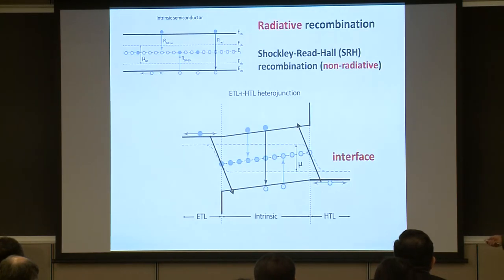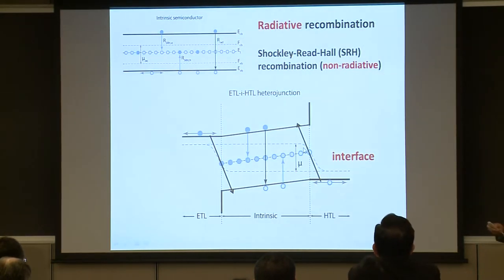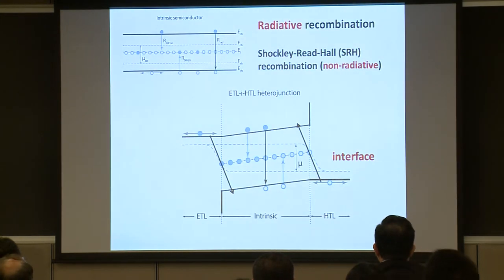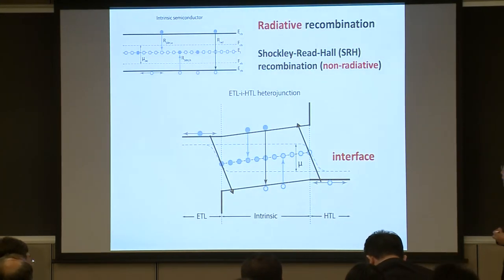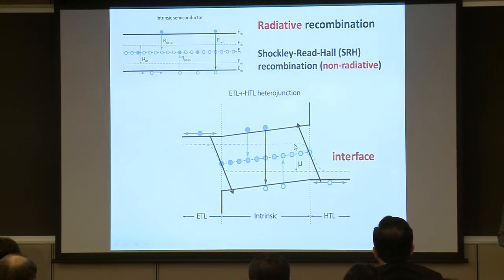And then the intrinsic semiconductor, as you know, has the radiative recombination and also the non-radiative recombination called SRH recombination. But when you make the junction, such as the ETL and HTL, then you also undergo some interface recombination. So three are very important. If you remove the interface recombination and non-radiative recombination, only allow the radiative recombination, probably you can get the 30% efficiency from the 1.6 eV perovskite material.